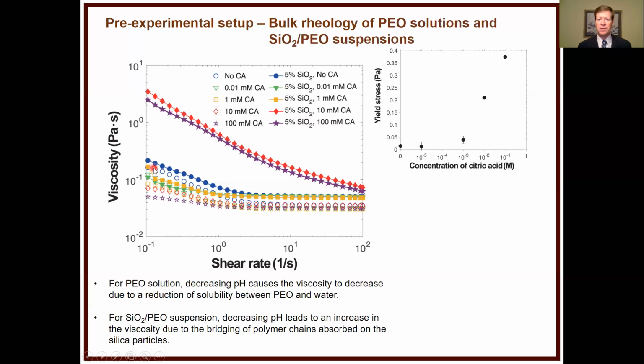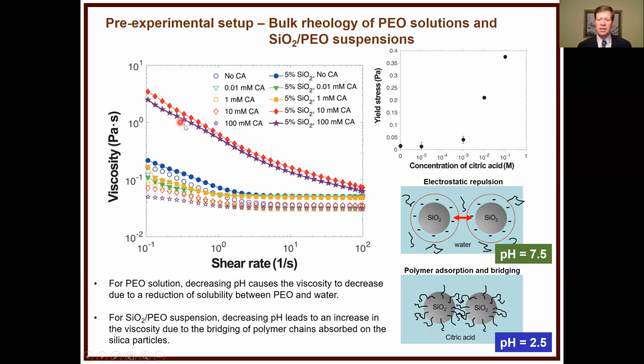But if we add silica, the blue lines shown here are these closed symbols, where essentially we just have a small modification of the viscosity by adding 5% of these microspheres. But as we change the pH, now the viscosity increases. And essentially, the picture you can think of is at moderate pH, pH 7.5, everything is repulsive and things can flow around freely. But then at 2.5, you essentially neutralize the surface of your silica, and then you have heteroaggregation of polymer to surface into other particles.